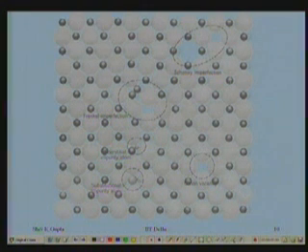Now, then there could be merely a cation vacancy and the crystal is still electrically neutral. This kind of defect in ionic crystals is a defect structure caused by the fact that cations have more than one valency. Such are the cases when we have cations from the first long period or the second long period or the third long period, the transition series, where the atoms are showing more than one valency. So, for example, iron can be seen in valency 2, can be seen in valency 3.